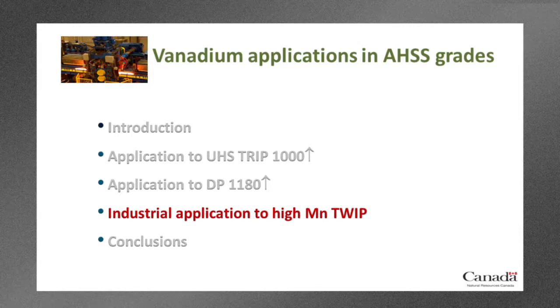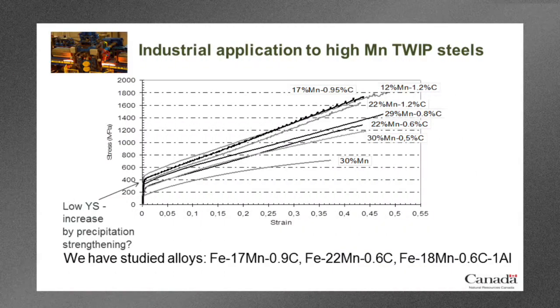And I'll come to the last application, which is a different type of microstructure. This is high manganese TWIP steels. Now this is a product that I worked on for a long time when I was at ArcelorMittal, and we studied three different alloys. Iron with 17% manganese and 0.9 carbon, iron with 22% manganese and 0.6 carbon, and iron with 18 manganese, 0.6 carbon, and 1% aluminium. This graph here shows the stress against strain curves for these steels, and what you can see is they have an enormous amount of strain hardening. They're very ductile.